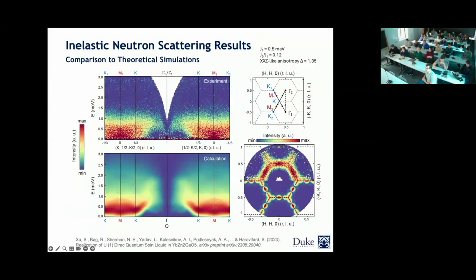So you're looking at the excitations for the calculation that is sort of in agreement with what we are seeing. There are two things that need to be addressed. The first thing is that we see an upturn in here, but we don't see it in our experimental data, for two reasons. One of them is that we have a blind spot in here. So it's very difficult to see the excitations up here because you're getting very close to the detectors. But the other thing is that on this downside that you're seeing, there's still a gap in here. And we think that this gap corresponds also to the gap that has been seen. So the upturn goes from the K point. So this is the K point, which is in agreement with here. And then there's a gap that is opening at the gamma point.